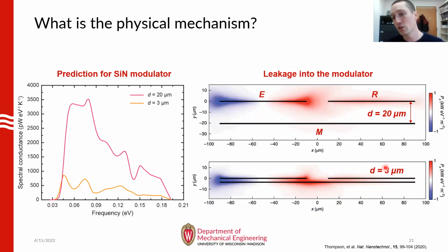But when the vertical offset is reduced to 3 micron, you see that the Poynting flux is no longer really in plane. It actually starts leaking into the modulator below, and less of the energy is transferred to the receiver. So the net result is that you get a suppression in the radiative conductance. Basically, you get this leakage of the Poynting flux due to the coupling of the guided modes supported in the top and bottom membranes. And this is possible because the mode tails of those guided modes actually extend several microns into the vacuum on either side of the membrane.